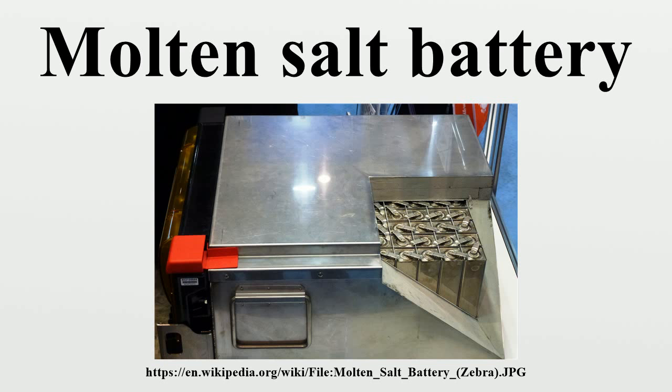After shutdown, a fully charged battery pack loses enough energy to cool and solidify in 3 to 4 days. Liquid metal: Both magnesium-antimony and more recently lead-antimony were used in experiments at Ambri. The electrode and electrolyte layers are heated until they are liquid and self-segregate due to density and immiscibility. They may have longer lifetimes than conventional batteries, as the electrodes go through a cycle of creation and destruction during the charge-discharge cycle, making them immune to degradation affecting conventional battery electrodes.